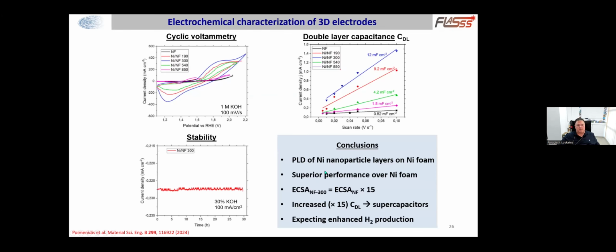And when performing electrochemical characterization of these laser-processed three-dimensional electrodes and doing these cyclic voltammetry measurements, we find that there is an optimum in the thickness, in the deposited thickness of these films.